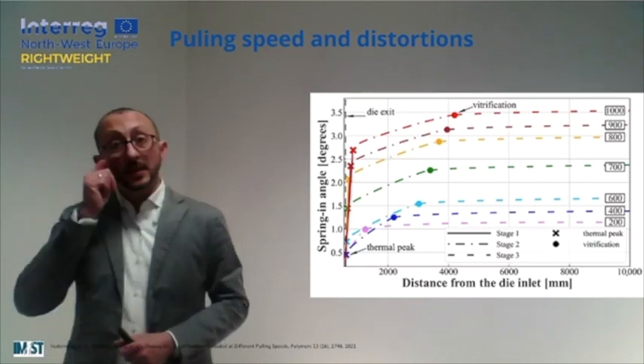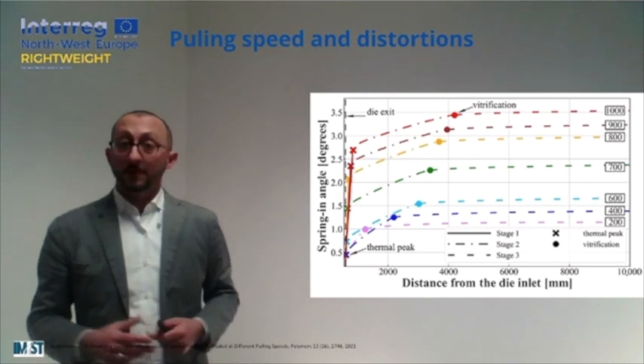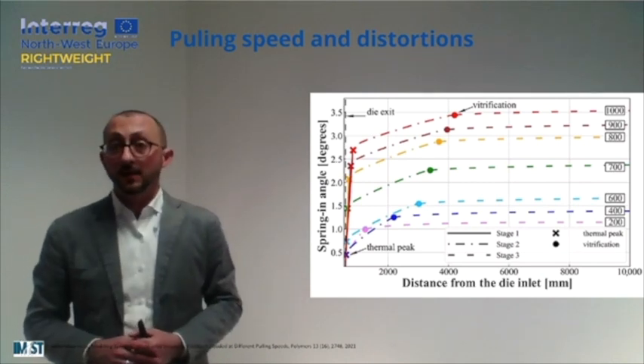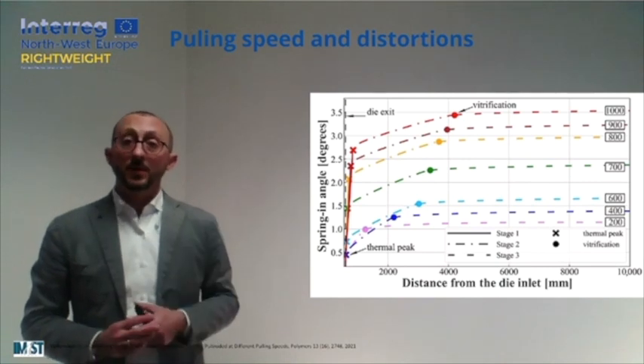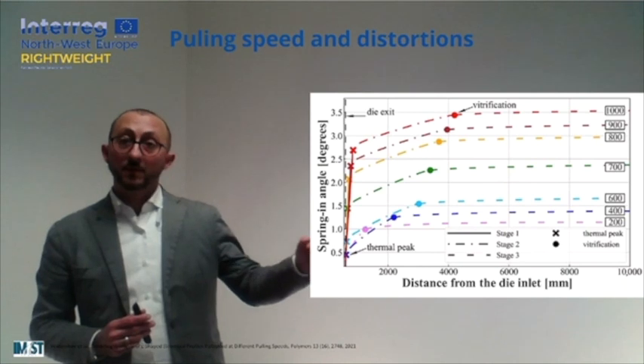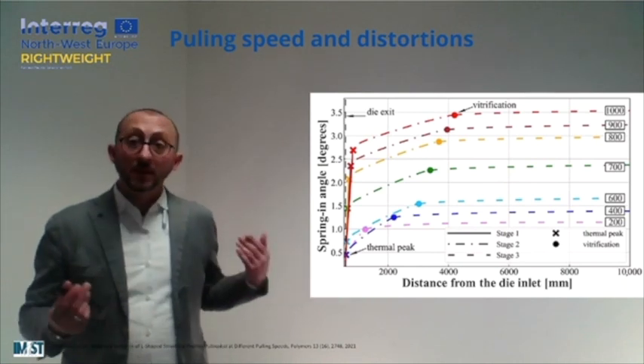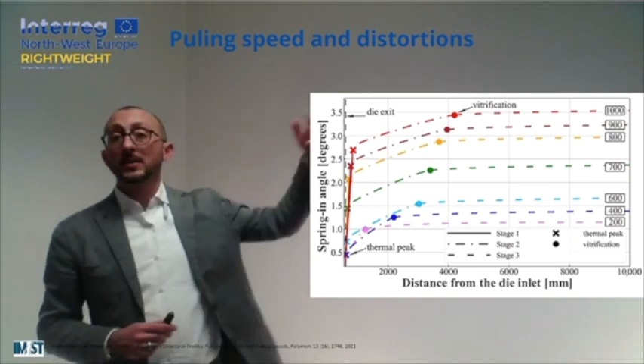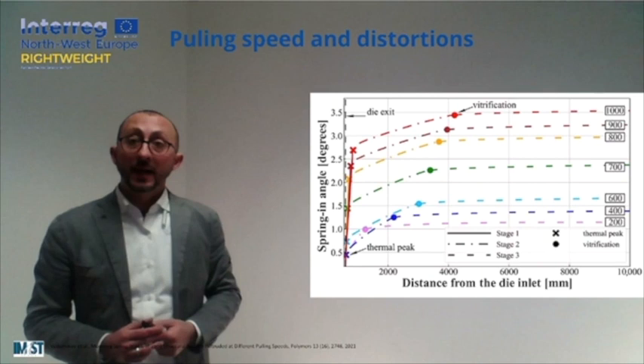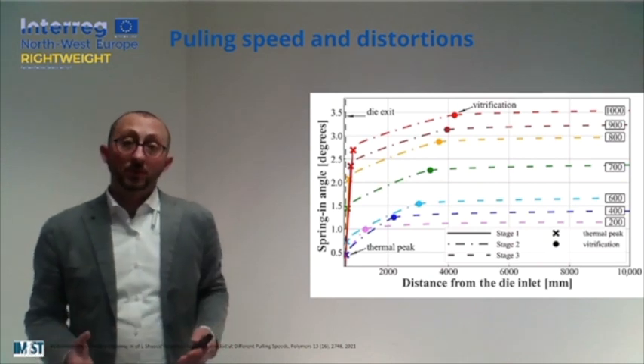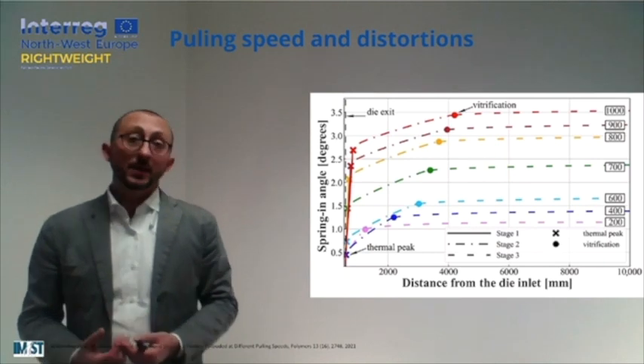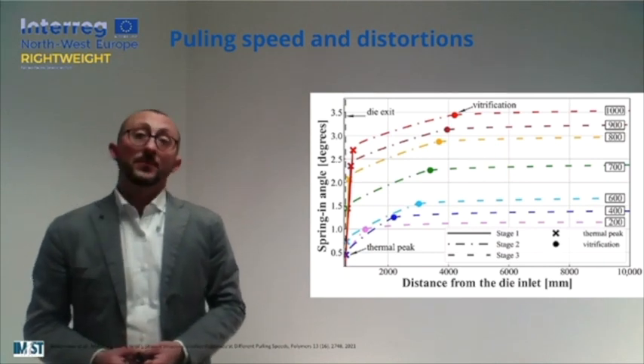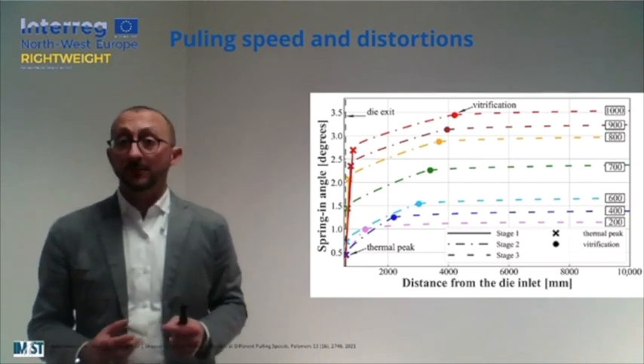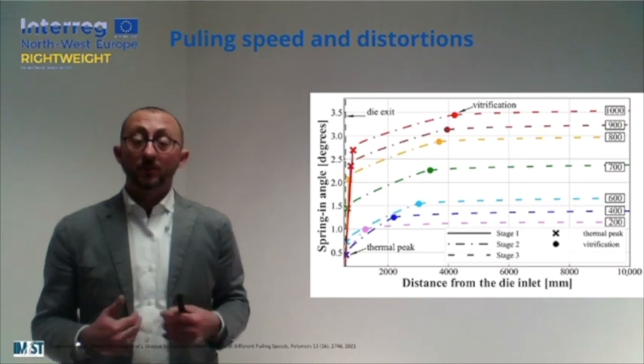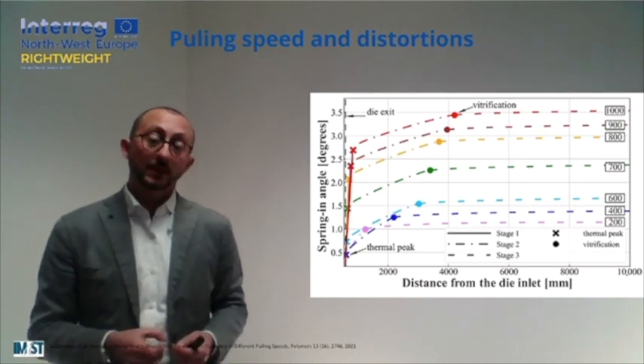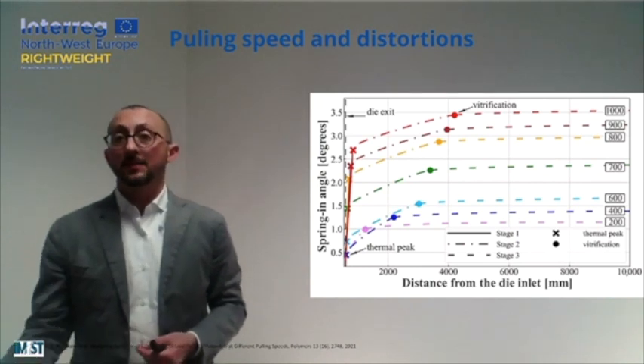Looking at this graph here, we can see that if we are traveling along the line too fast, the vitrification point will be displaced to the die exit, and eventually we will have this vitrification outside the heating and curing die. And if this is happening, the amount of distortion will be much higher. As a general rule, it is better to have at the die exit a fully vitrified solid, so reducing the amount of distortions that the material can have outside.